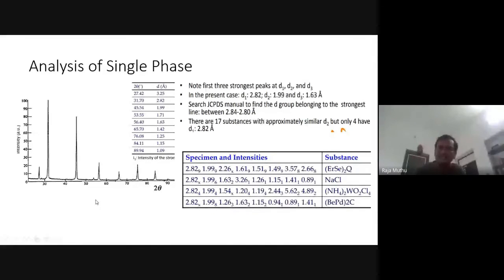So how to do it? What's the procedure? First, take the strongest three peaks. The d spacings are 2.82, 1.99, and 1.63 angstrom. So we can search the JCPDS data bank, from 2.84 angstrom to 2.8 angstrom. It is observed that about 17 substances are approximately similar to the d spacing we suggested.